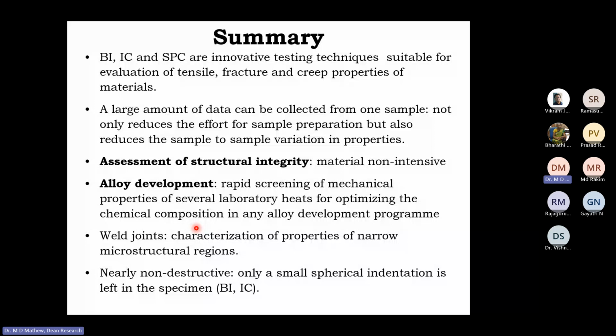It's very useful for other development programs, as I have demonstrated, that rapid screening of mechanical properties of multiple laboratory heats for optimizing the composition can be carried out in short time. And weld joints can be characterized. The properties of different microstructural zones in the weld joint can be characterized. And it is nearly non-destructive. You will find the ball indentation leaves a small spherical indentation. Likewise, in the case of small punch creep also, and in the case of impression creep also. But the small punch creep, of course, is destructive because the sample breaks. But you don't need a lot of material to do this test. So to that extent, you can say that the structure is kept intact.